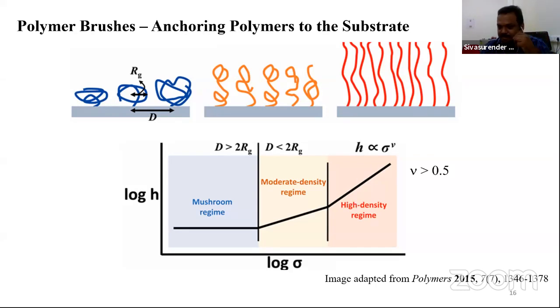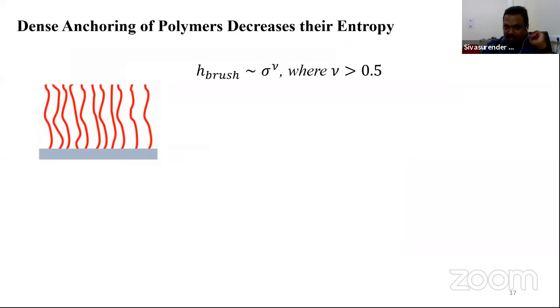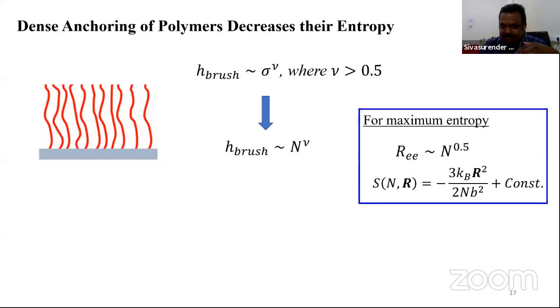And this is much more than the root n that we have seen, right? So just to bring you into our definition of the polymer, this height of the brush scales with the grafting density to the power of an exponent, where the exponent is much larger than 0.5. You can now rewrite this in terms of the number of monomers forming this polymer. The height of the brush is now scaling with n to the nu, which is the exponent. And you know that for equilibrium, this nu would be 0.5.